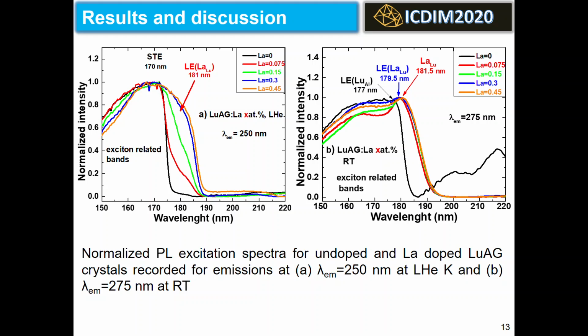This slide shows liquid helium and room temperature excitation spectra for emission at 250 and 275 nanometers respectively. At liquid helium temperature, the excitation spectra of self-trapped exciton luminescence in undoped and lanthanum-doped LuAG single crystals show strong absorption at the fundamental absorption edge, confirming its self-trapped exciton nature.